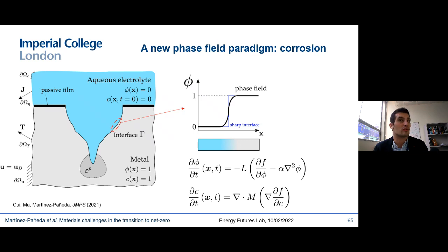We have used it to predict microstructural evolution, fracture, and voiding in batteries, and it seems to be a massive success, so why not use it in corrosion too? And I won't get into the details of the formulation, but essentially it has two ingredients in the simplest form. The short-range interactions, that is the corrosion process, material dissolution, atoms detaching, which is captured by the phase field variable, and the long-range interactions, that is the diffusion of metal ions away from the electrolyte-metal interface, to capture the interplay between activation and diffusion control corrosion. So the corrosion front is given by this variable that is equal to 1 if we are in the metal, and equal to 0 if we're in the electrolyte.